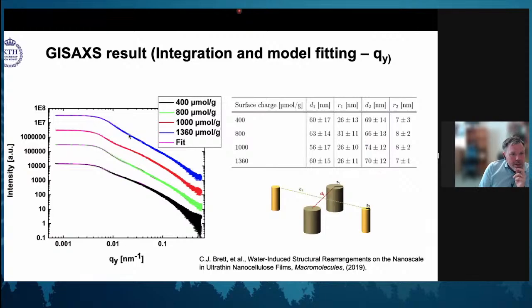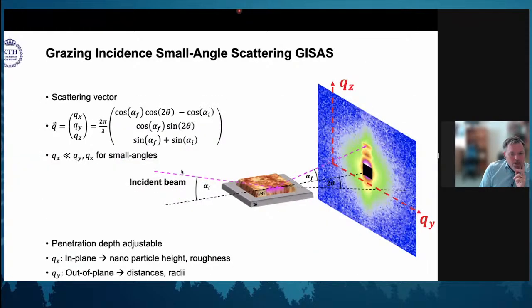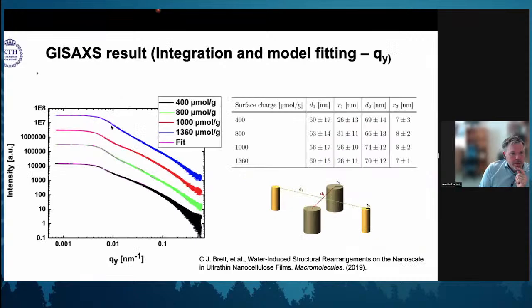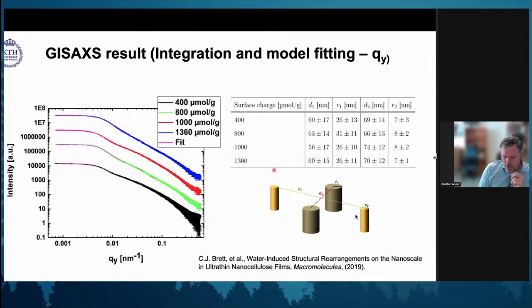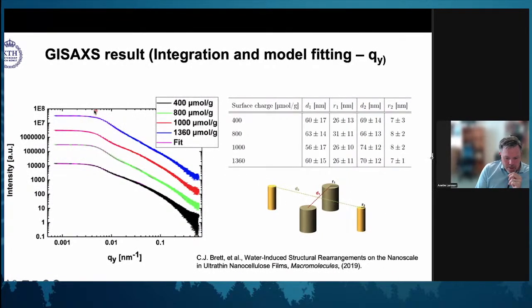If you then integrate it and look at what happens, I will go back, if it happens in the Y direction here, we are looking into what happens in the plane of the film as we see it with the incoming beam. What we can see is that we get integrated scattering curves. We can take this model that we have developed and we can fit it. And we can fit it for different charges.